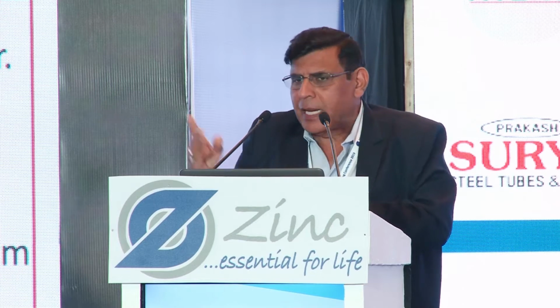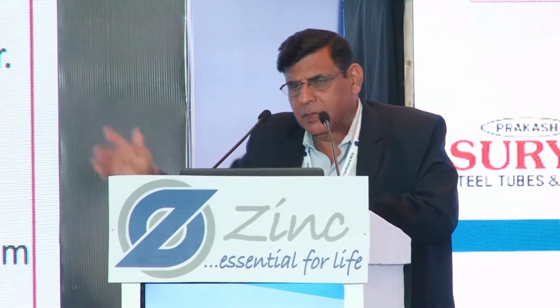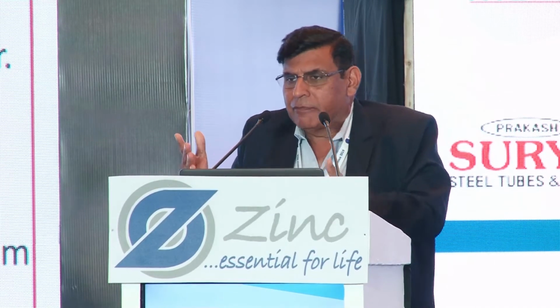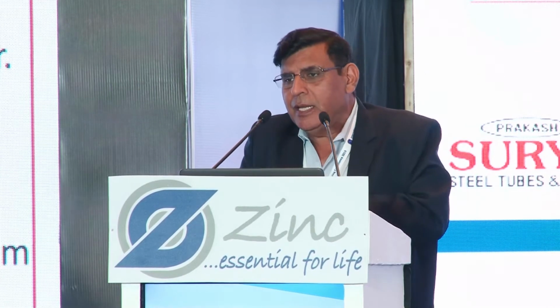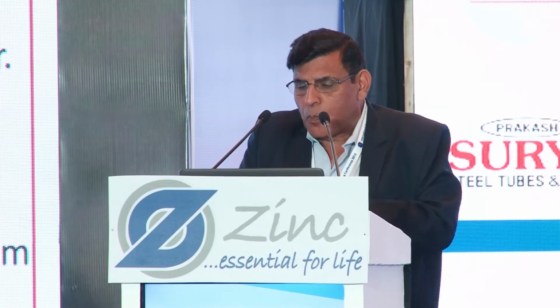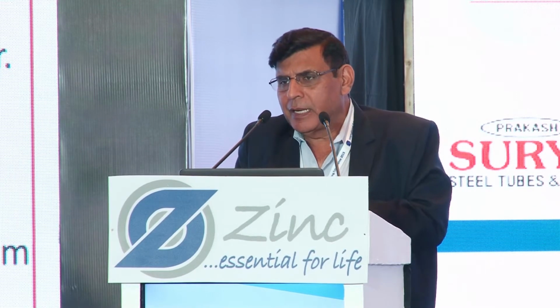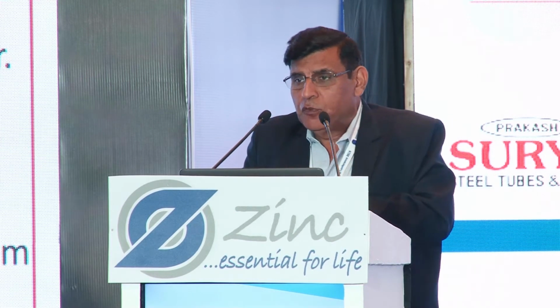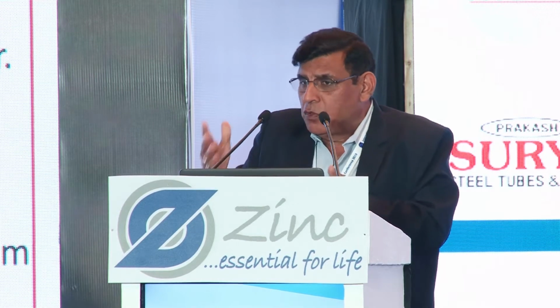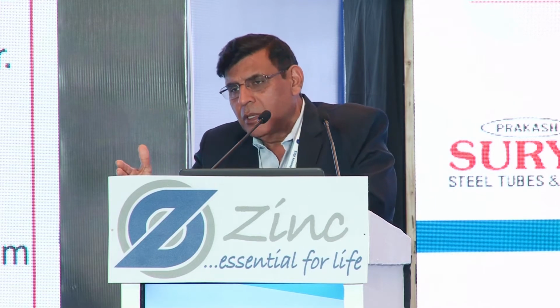Today we have lots of facilities. You can have a black bar, which can have a life of 7 years onward or so. Then you can have TMT bars, then CRS bars, then fusion bond epoxy, stainless steel, and galvanized bars. Based upon that, we have proposed recently that if you use duplex stainless steel, you can get a life of 300 years. If you use ordinary stainless steel or ferritic stainless steel, 120 years. And if you use fusion bond epoxy or so, 30 to 60 years. Galvanized, we have given a rating of 60 to 100 years.